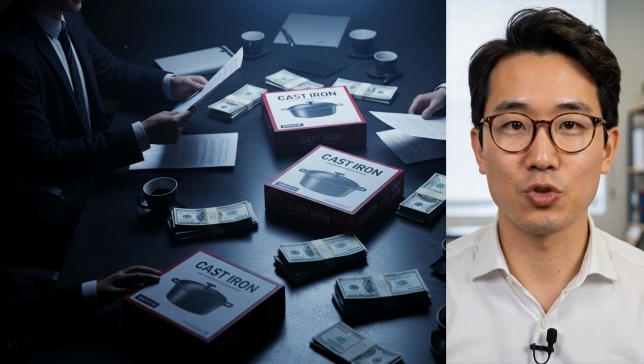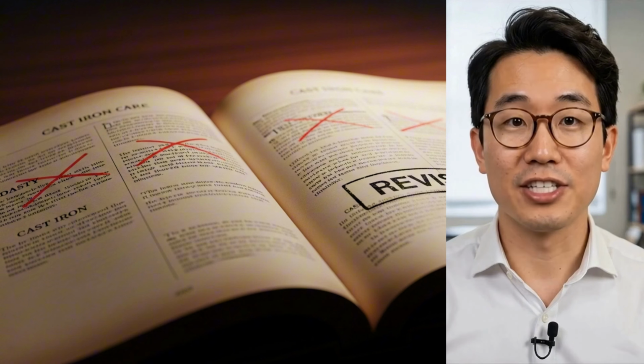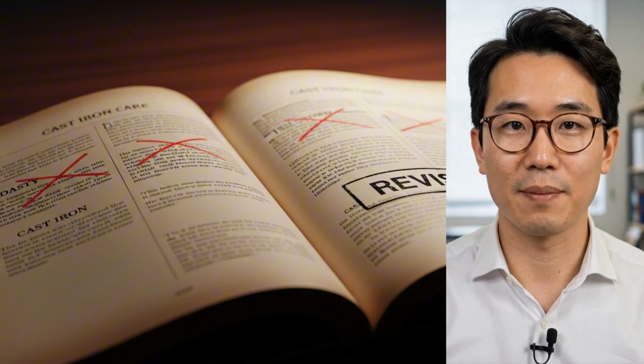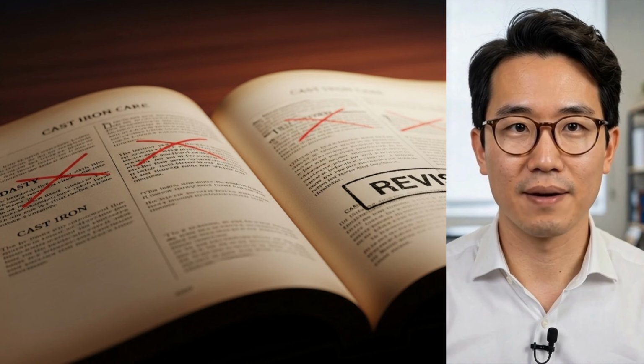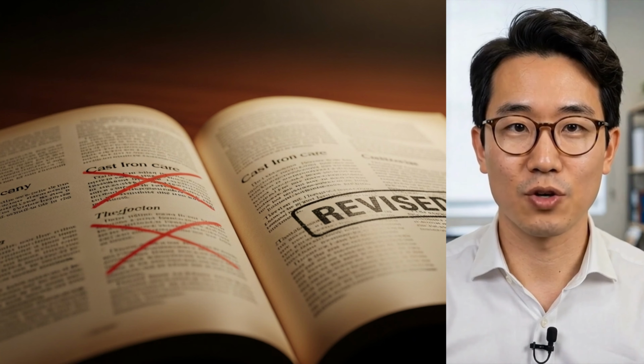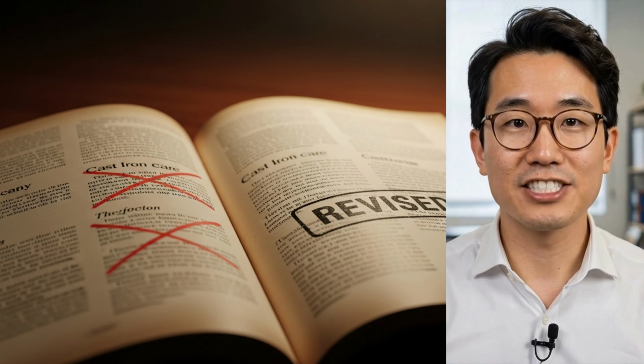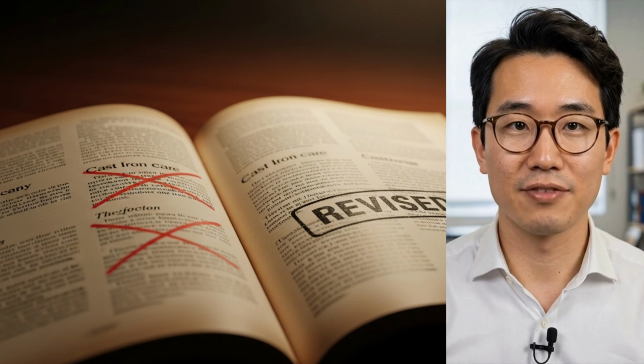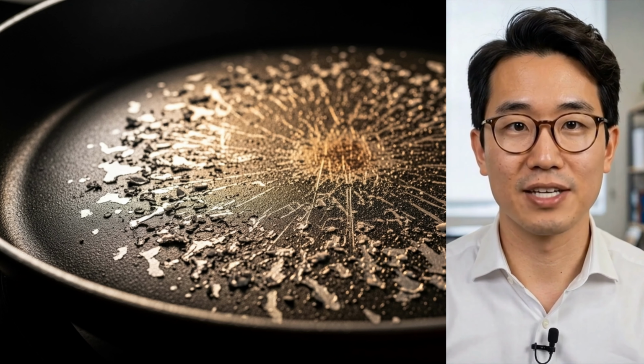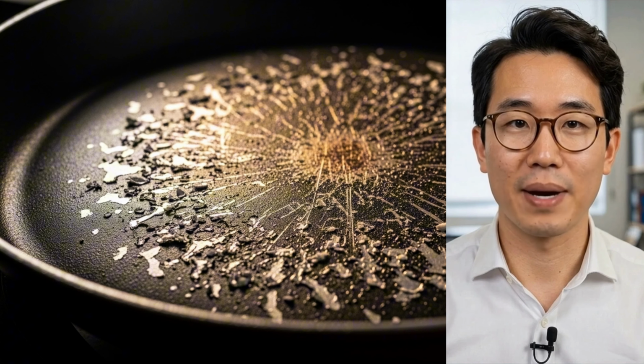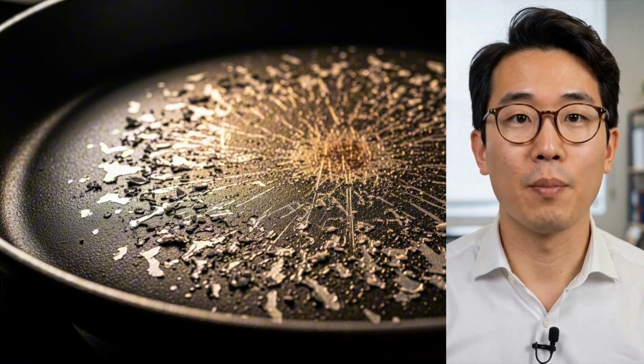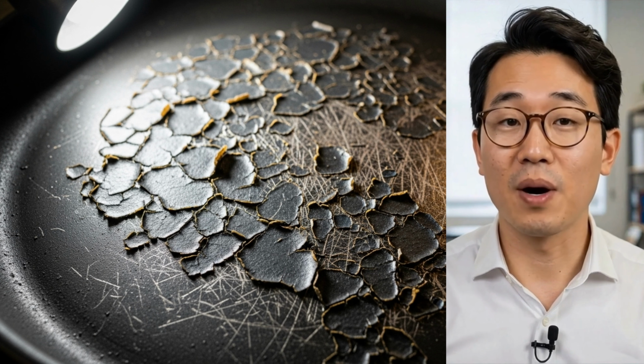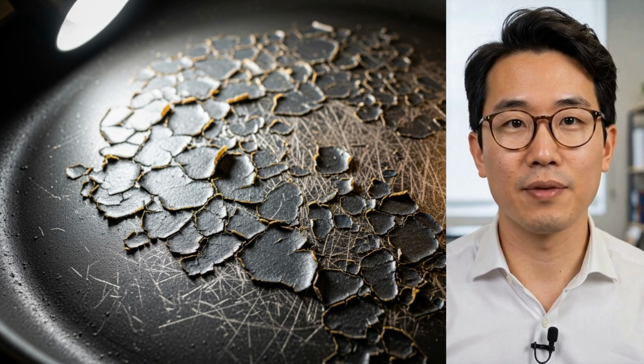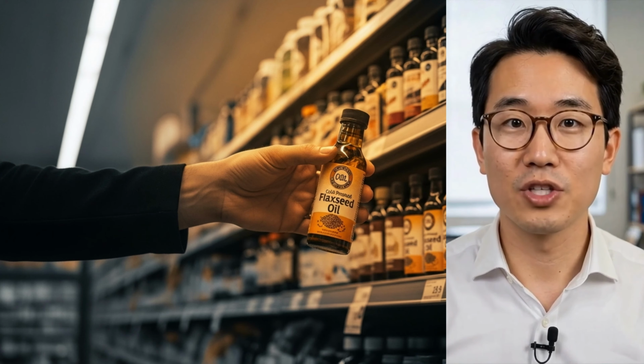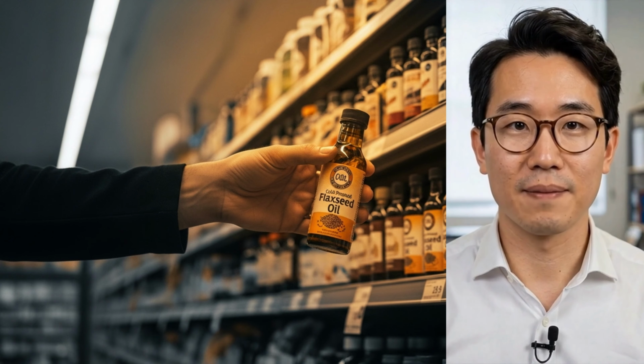But stay right here, because what comes next is the part the cookware industry really does not want you to hear. Here is what is actually happening when you apply flaxseed oil to cast iron. And it is more impressive than any marketing copy you have ever read. Flaxseed oil has the highest linolenic acid content of any commonly available cooking oil, roughly 57% by composition. Linolenic acid is an omega-3 fatty acid with 3 double carbon bonds per molecule. When you expose it to heat above 375 degrees Fahrenheit, those double bonds break open. Oxygen from the atmosphere attacks those open bonds.